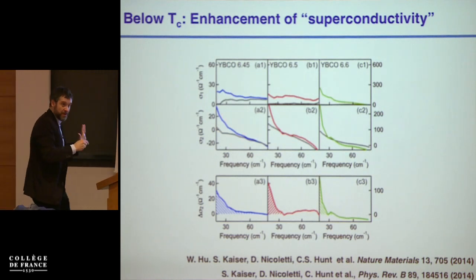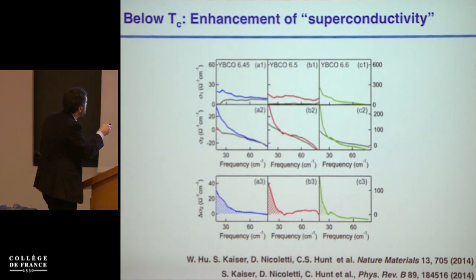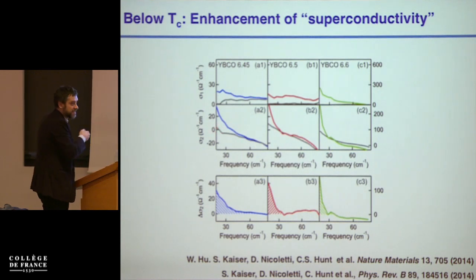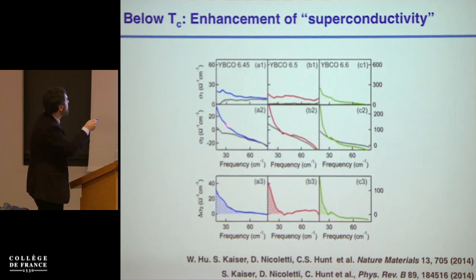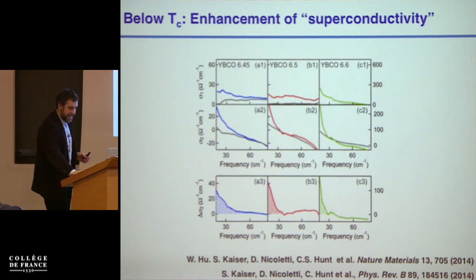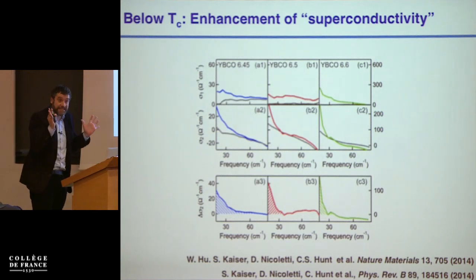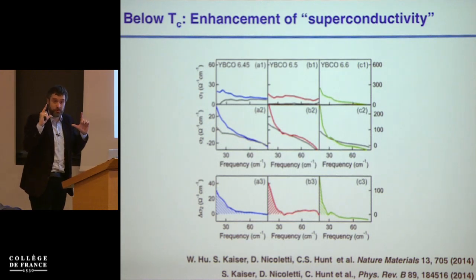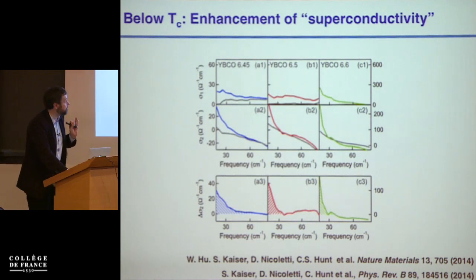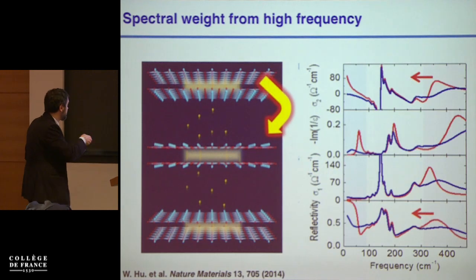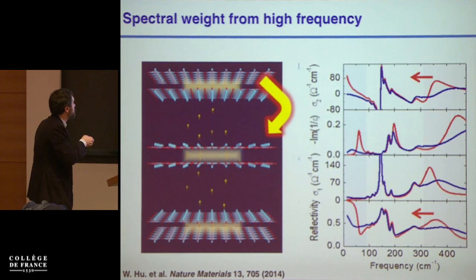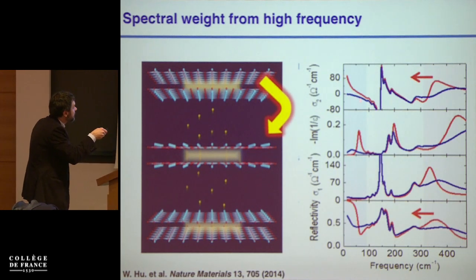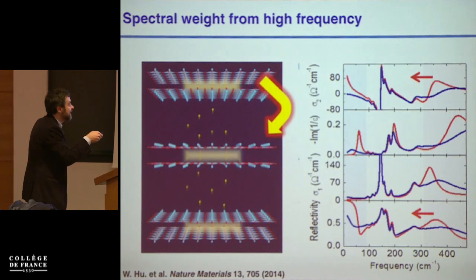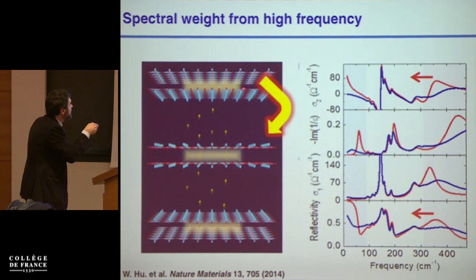Okay, so at equilibrium, which is where everybody agrees that this is an equilibrium superconducting state, sigma 2 looks like this. You have this pitifully small divergence down to these frequencies in sigma 2. You have this other small divergence in sigma 2 in gray. When we photoexcite, we see clearly a very strong increase in the out-of-plane coupling between the layers. Okay? This is indicative of the fact that below TC, when I pump the apical oxygen, the system becomes more superconducting perpendicular to the planes. This is a measurement done by Wanjiang Hu, who is still a postdoc in my group. What she found is that all this superfluid, this is a fit here, the superfluid density that is acquired at low frequencies when I excite, all comes from the strength of this other peak, as if I was transferring coherences from this junction to this junction, okay?